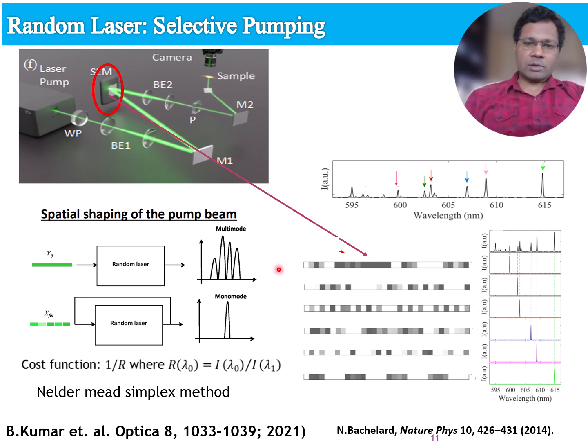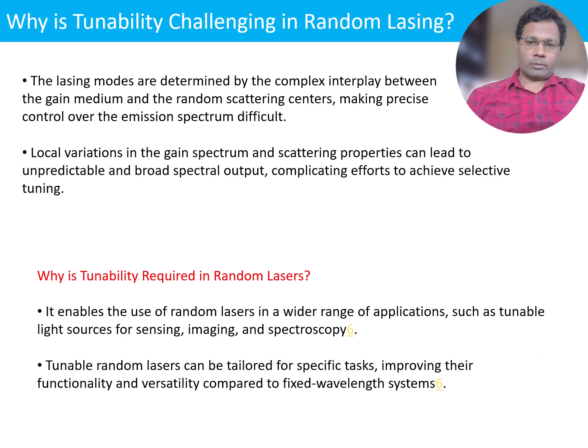We have achieved single mode operation at any desired wavelength picked from the uniform pump emission spectrum. It took almost 200 iterations for one complete optimization, and the algorithm converges to a non-uniform pump profile that optically promotes the target mode lasing wavelength while suppressing other modes below threshold. Here we can see 5 unique modulated pump profiles for 5 different wavelengths selected individually.